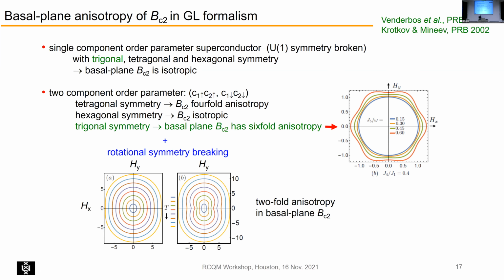And in order to come to this 2-fold anisotropy, you have additional rotational symmetry breaking. So the idea is that actually you would have 3 domains, but because of some mechanism, you break the symmetry and you have only 1 domain. But you could have 3 in principle.